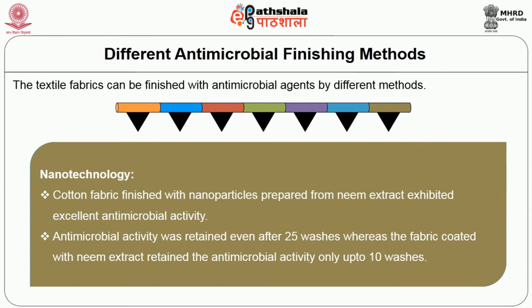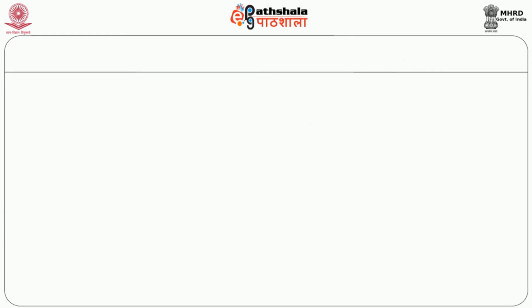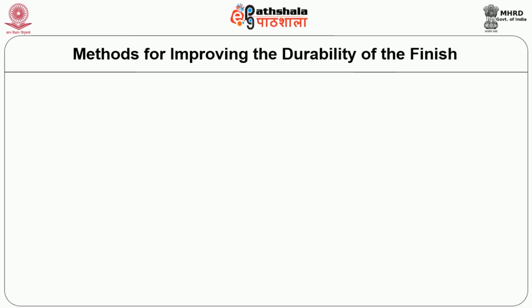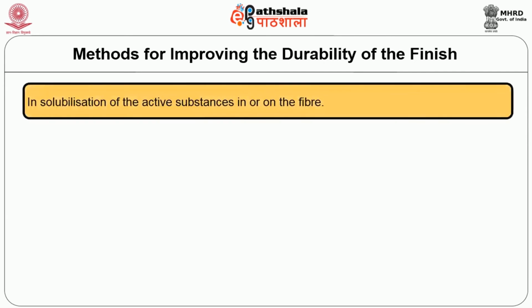Nanotechnology. Cotton fabric finished with nanoparticles prepared from neem extract exhibited excellent antimicrobial activity. Antimicrobial activity was retained even after 25 washes, whereas the fabric coated with neem extract retained antimicrobial activity only up to 10 washes. Methods for improving the durability of the finish.